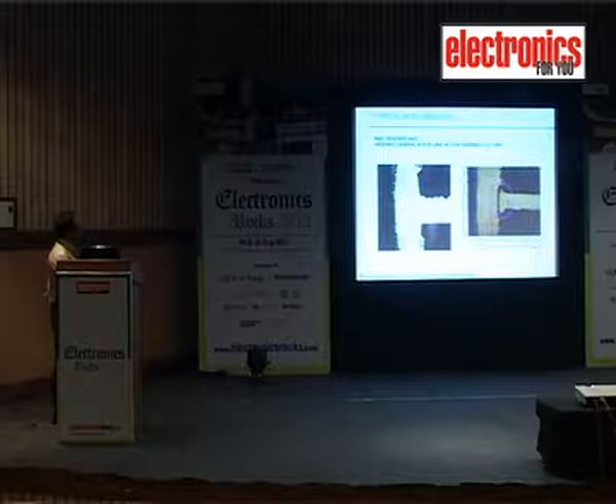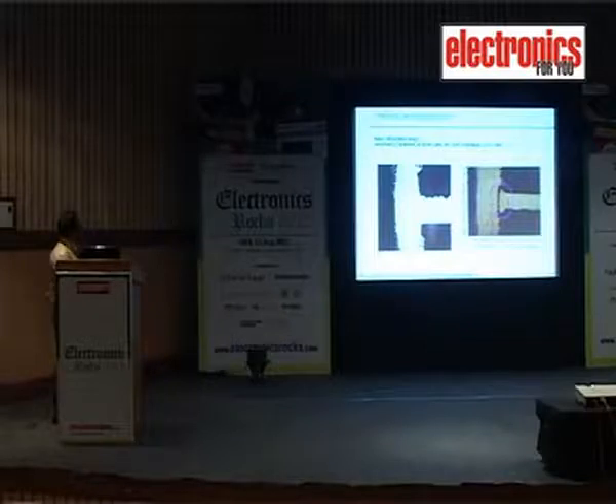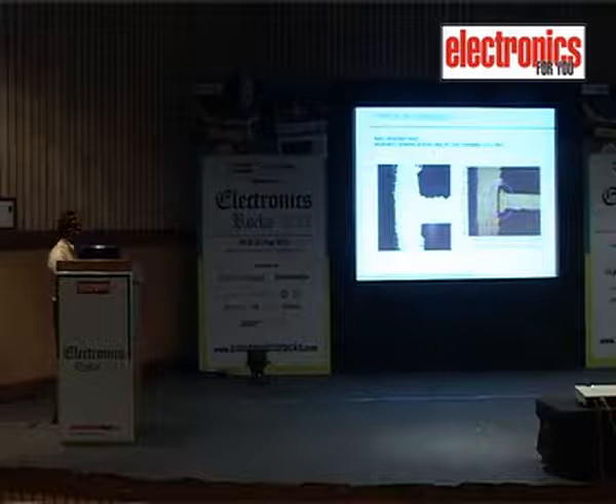You can see there can be a demarcation, that is, it is an inner layer here, it is a plated through barrel. Once we subject it to thermal cycling, we can see due to the nail heading effect, it can get demarcation. There won't be proper adhesion of the inner layer copper to the whole wall barrel. This can lead to the total failure of the electronics which is housed on that PCB.